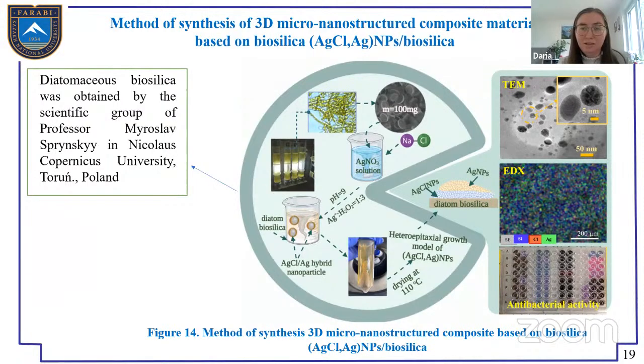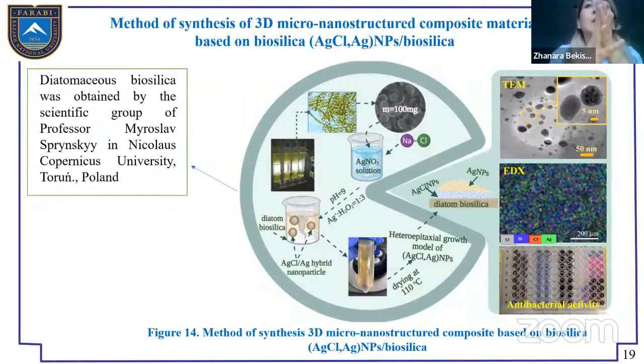Yeah. For one synthesis, one composite, I spend approximately 6 hours. After that, I put it on drying for 12 hours. If I calculate all the time, it will be 18 hours for one composite. Did you do it once, two, three times? I can do it in parallel. I can put three glasses and take three concentrations. And after that, centrifugation and washing. For example, in one day I can prepare three composites in different concentrations.